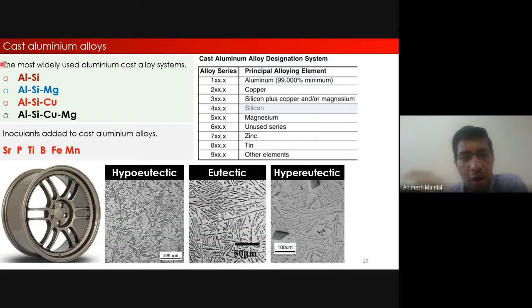If you are aware of a binary phase diagram, the aluminum silicon alloy, if you look at the phase diagram, though I'm not showing it here, you have a eutectic composition. All the alloys towards the left are called your hypoeutectic alloys, and the alloys towards the right of the eutectic are called your hypereutectic alloys. Accordingly, your microstructures can vary. You can see the silicon you have here in the eutectic as well as the hypoeutectic is all needle in shape.